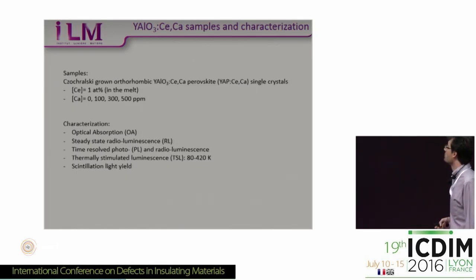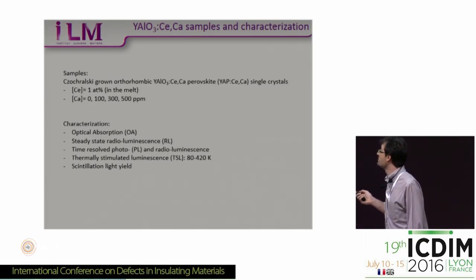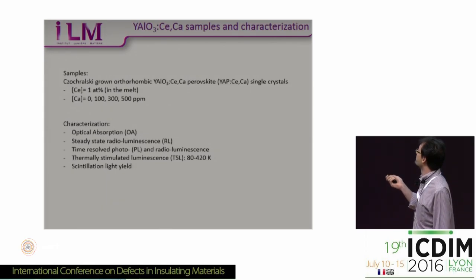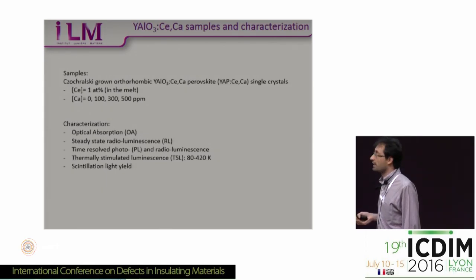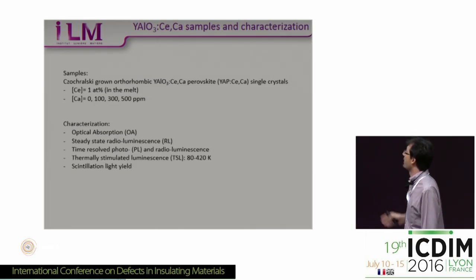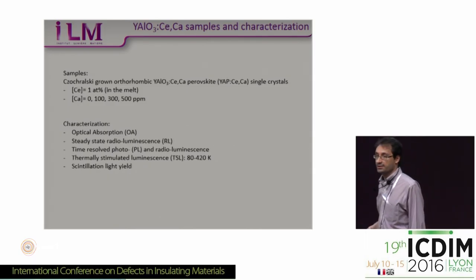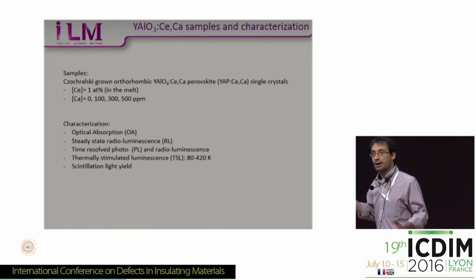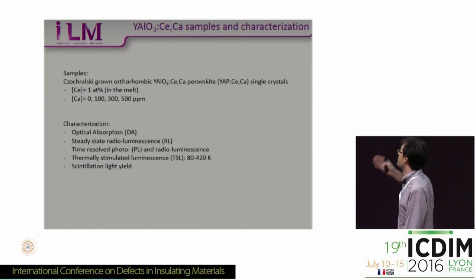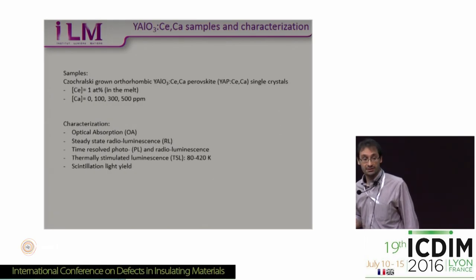So we've grown four different crystals, all of them with the same cerium concentration, and with four different calcium contents, from 0 up to 500 ppm. And then what we did is simply the standard characterization you would expect: optical absorption, steady state and time resolved radio- and photoluminescence, thermally stimulated luminescence, and some scintillation results.